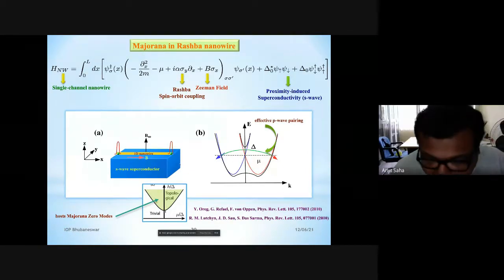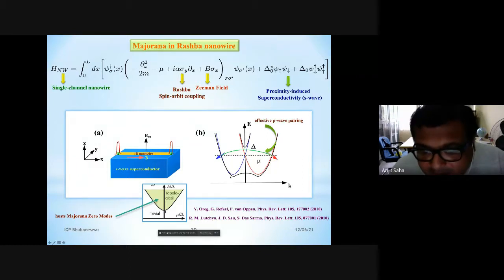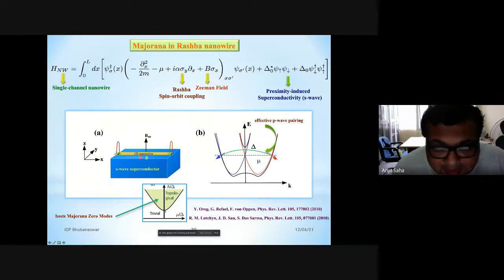So from the band structure, in the presence of spin orbit coupling, the spin up band and spin down band are separated, the blue and the green, and the magnetic field opens up a gap at k equal to 0 here. If you increase the strength of the magnetic field, effectively the two spin bands are separated. And if you choose your chemical potential as here, it will encounter an effective p-wave pairing. So by inducing S-wave and choosing the chemical potential properly, I can engineer a p-wave pairing